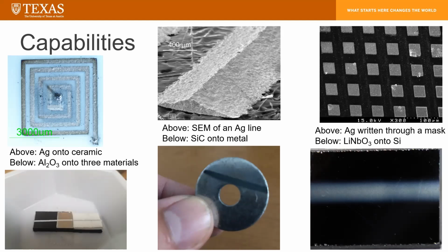So this shows we have a pretty versatile process that can deposit ceramics onto a wide variety of substrates. In the middle, we see silicon carbide deposited onto a washer. This is silicon carbide, a very hard ceramic used for abrasives and various coatings, deposited onto a soft galvanized coating. So you can imagine there's a lot of process disparity there for what kind of properties you can get. And on the right, you see lithium niobate, a technical ceramic with some interesting electrical and optical properties, written onto silicon. So there's a lot of capabilities that we can do.